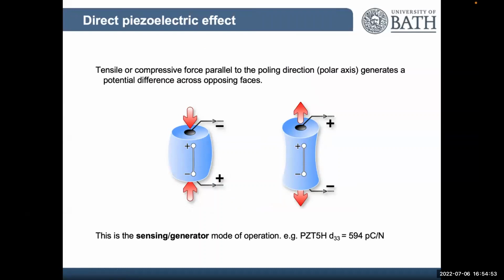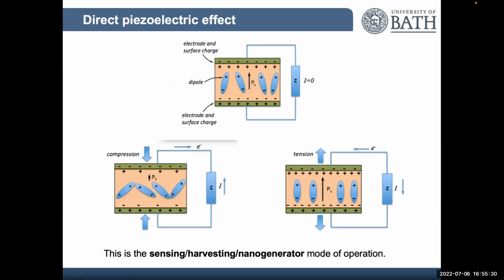Once we've poled our material, we can use it as a sensor or as an energy harvester. If I apply a compression, imagine pushing that titanium 4+ ion back into the center of that tetragonal unit cell, the polarization falls, and I develop a charge. Likewise, if I apply a tensile load, the titanium 4+ has moved even further away from the center. So again, I'm enhancing the polarization, and I'll develop a charge for a sensing application or an energy harvesting application. This can be at the device scale, or as Haito was explaining, at the particle level in an electrochemical system.